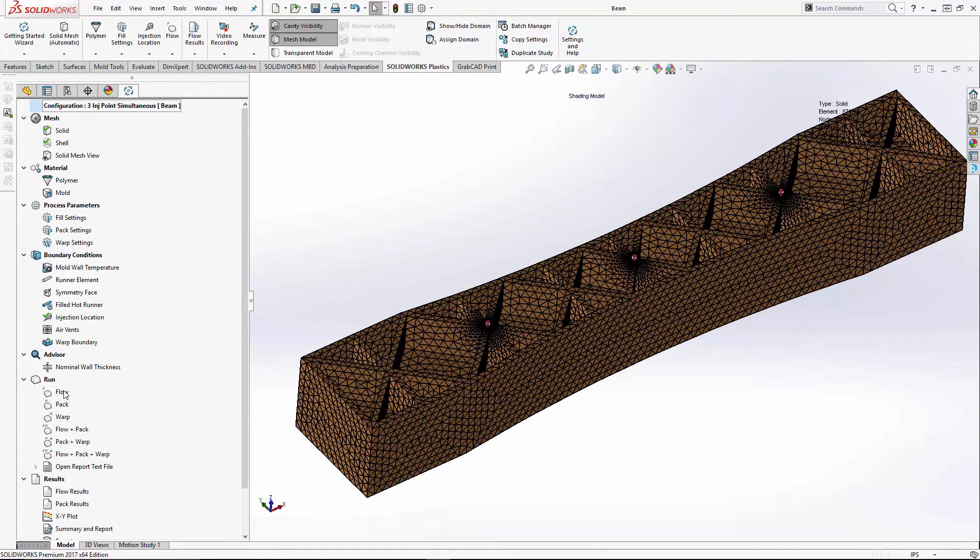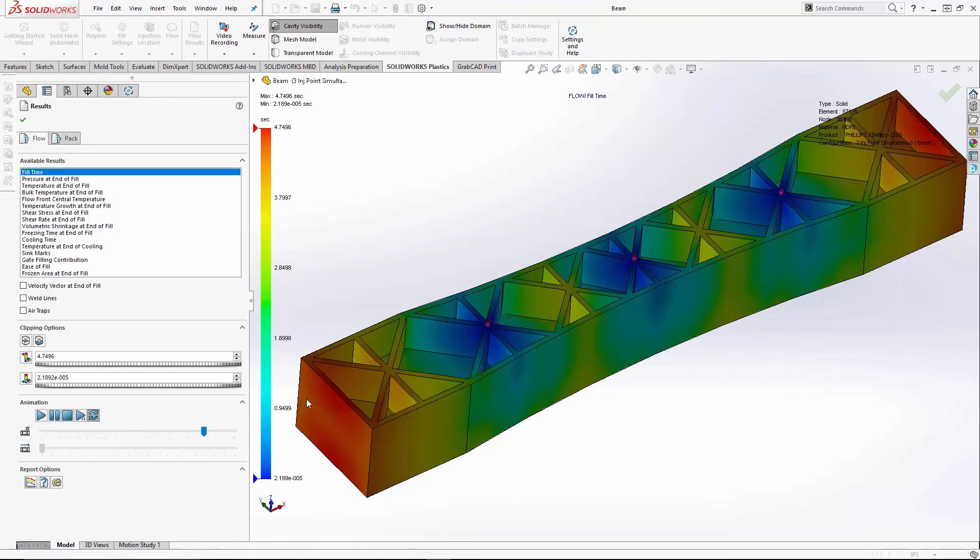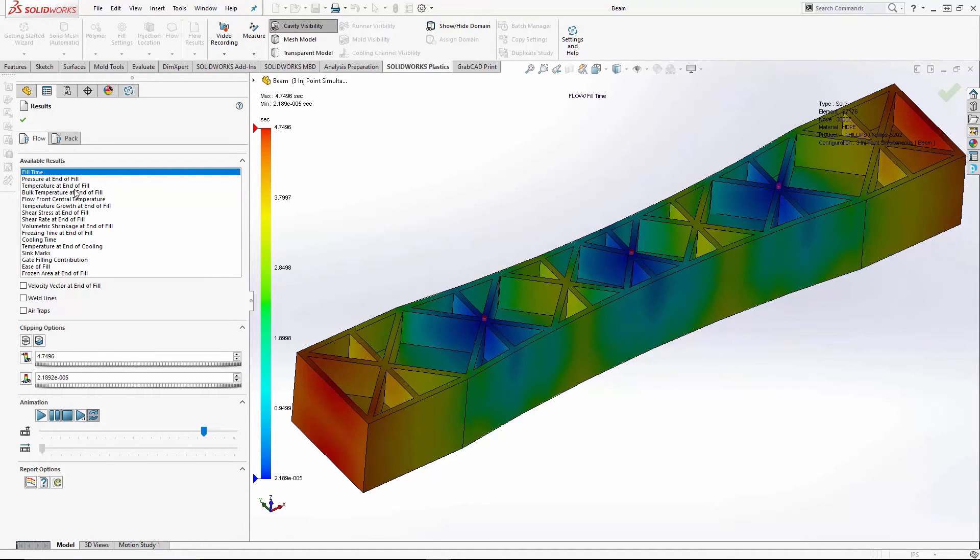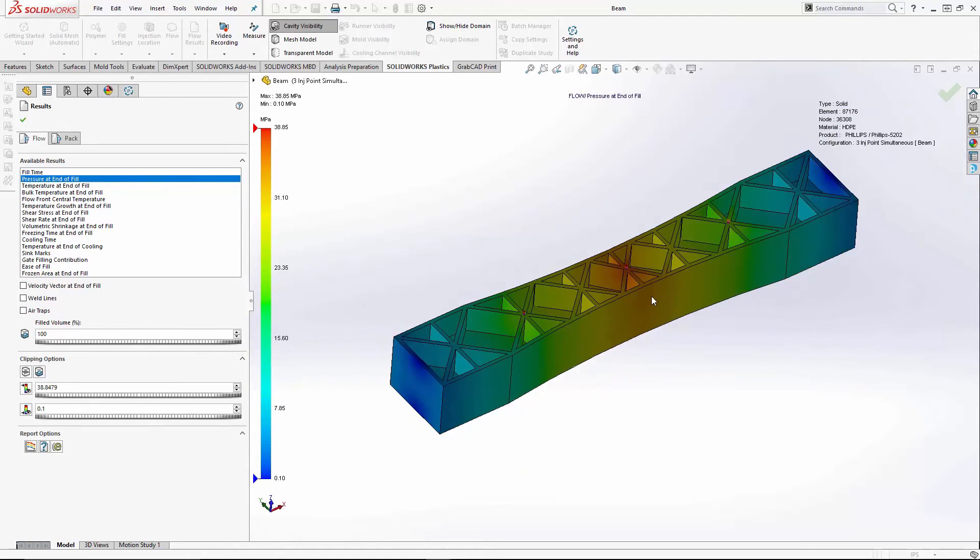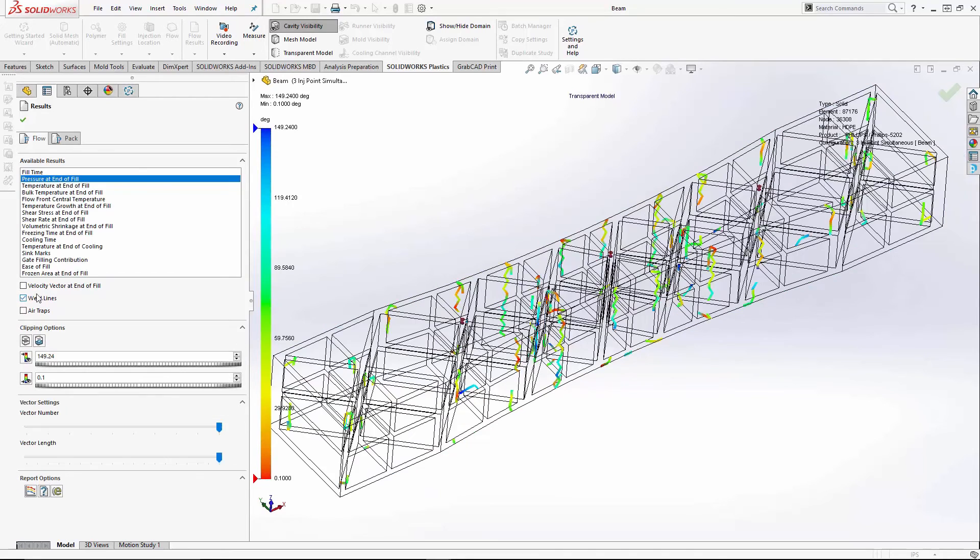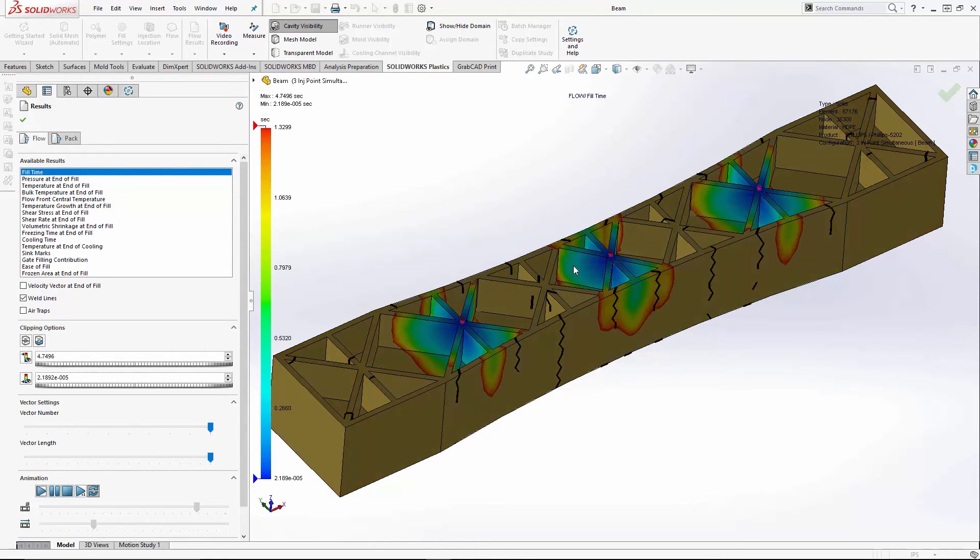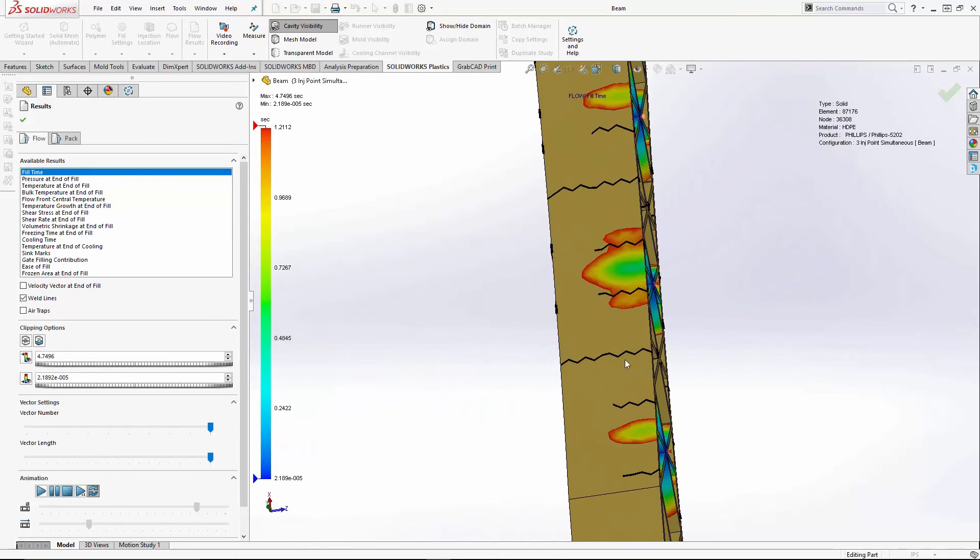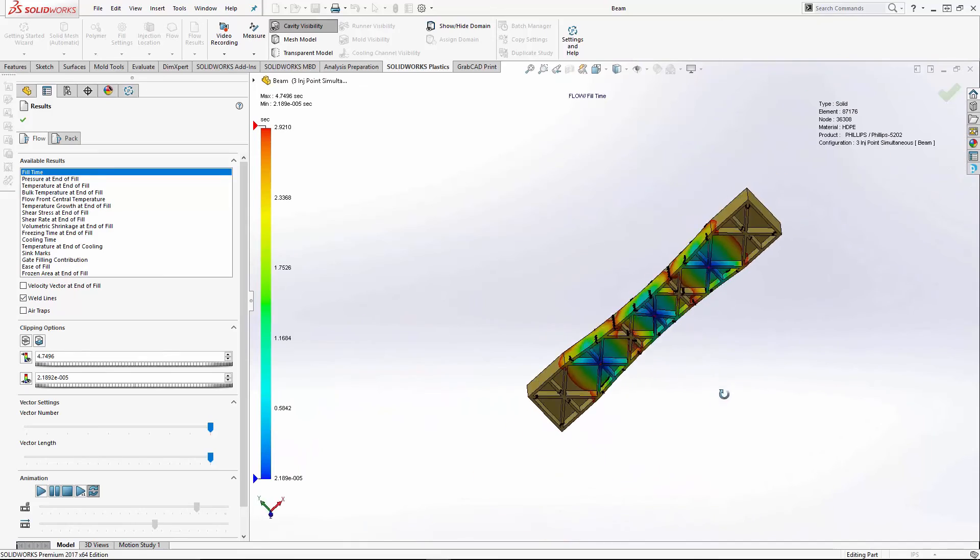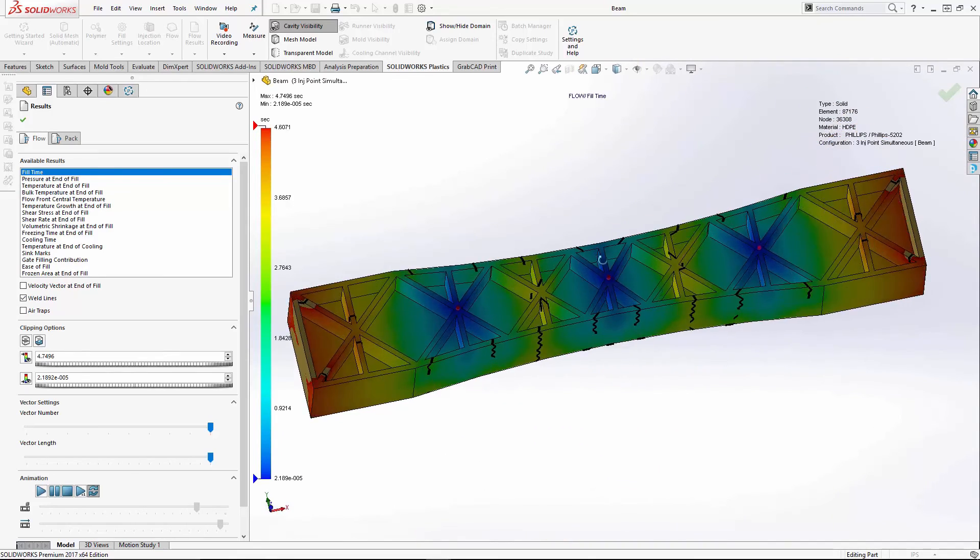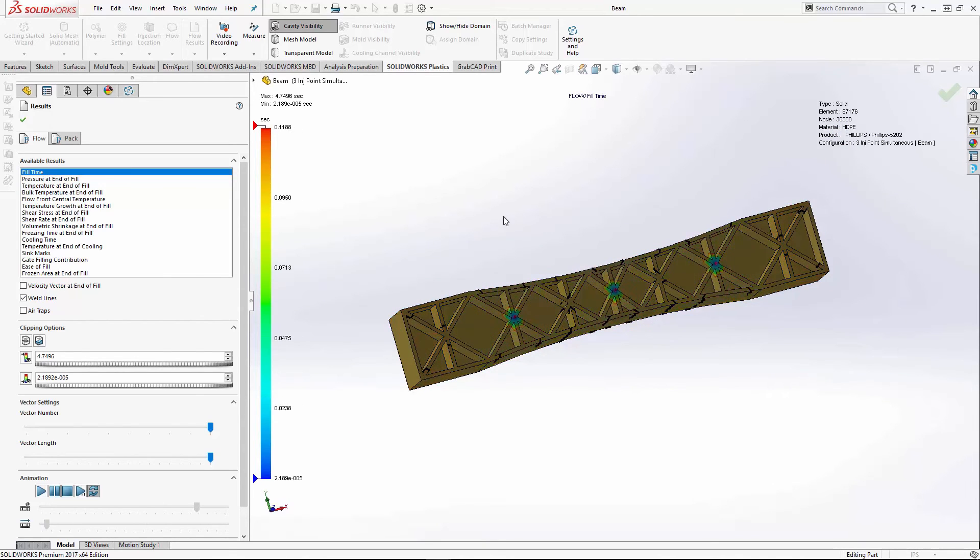I've already run the flow, so we're going to go to flow results. So with our flow results, shorter cycle time, that's good. Our pressure at end of fill is a little less, that's good too. But if we look at our weld lines, since we have the flow fronts meeting at these areas, they create weld lines all the way through the part. Since this appears to be a structural beam, that may cause some weaknesses in that area, stresses that may crack or break under pressure.